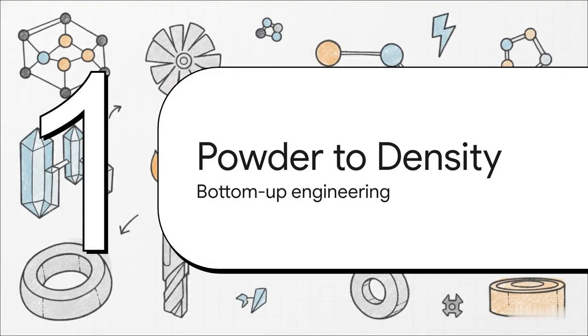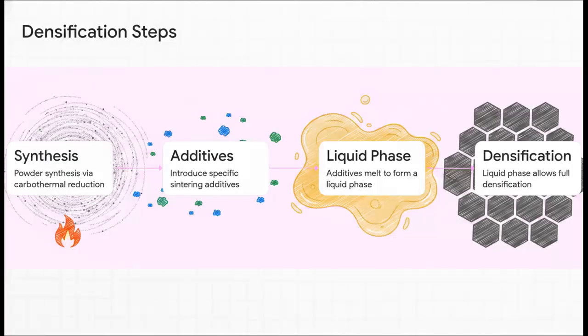Moving right along to Section 1, powder synthesis to densification. So how exactly do we get these crazy macroscopic properties? Well, we've got to look at the bottom-up engineering flow. The creation of a fully dense component follows a very strict sequence. It starts with powder synthesis, often using carbothermal reduction. After that, we introduce highly specific sintering additives. Those additives melt to form a liquid phase, which finally allows the ceramic to achieve full densification.